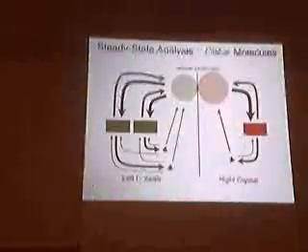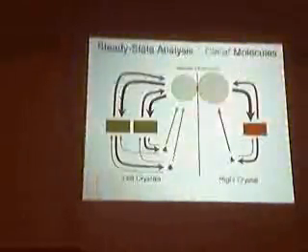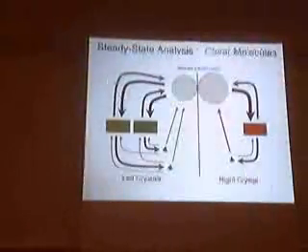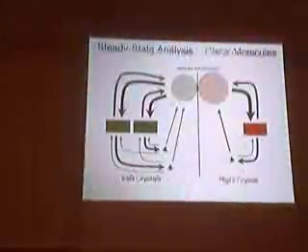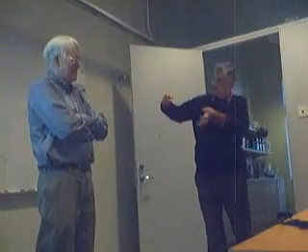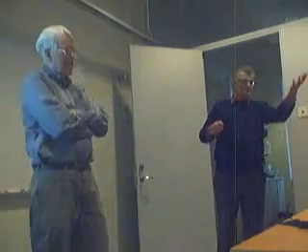Yeah, I know. And I think that in our case, when we have studied solvent effect on crystal growth in many systems, we have shown that the stripping of the solvent molecules from the surface is the rate-determining step. But you know, just a moment, Mike. So I want to ask a simple experiment, really. If you check some solvent which is less attached to the surface, and the energy of stripping of that solvent from the surface is much smaller as compared to the other solvent, then naturally maybe the rate-determining step will be the attachment of the cluster to the surface, whereas in a different solvent where you have very strong interactions with the surface, then you have a different mechanism.